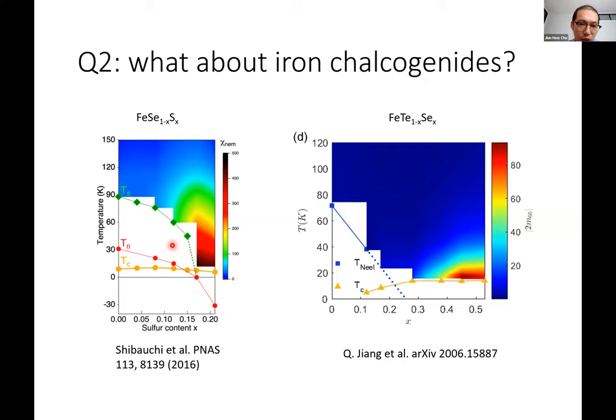Now, obviously, to answer the question, one can measure iron chalcogenides, where there's no longer a magnetic phase around. In this system, both in Shibauchi's group and also my group, we have demonstrated that there is a very strong nematic susceptibility. They have found a very strong nematic susceptibility in the iron sulfur selenides. We found there is a nematic susceptibility divergence near the iron tellurium selenides. So it will be interesting to test if you can also see a suppression of superconductivity. We have some preliminary measurements, and the effect is definitely not as strong as in the pnictides. But as we see in the pnictides, a very careful doping dependence is needed to get the whole picture.